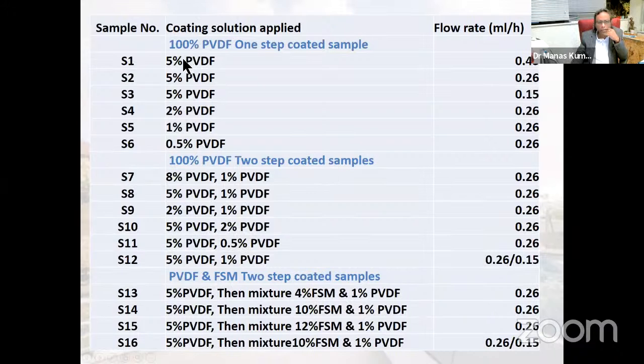For the single layer fabric, we tried only different concentrations, 5%, 1%, 0.5%. After that, we tried the double layer. Double layer means first we try with 8% PVDF, and on that we try with 1% PVDF. So first we prepare the microstructure, then we prepare the nanostructure on that, and that gives the benefit. And here we use the PVDF and FSM. First is the 5% PVDF, and then we use a mixture of FSM and PVDF. We observe that when the percentage of PVDF is lower than 1%, we have not observed much benefit in terms of super hydrophobicity.